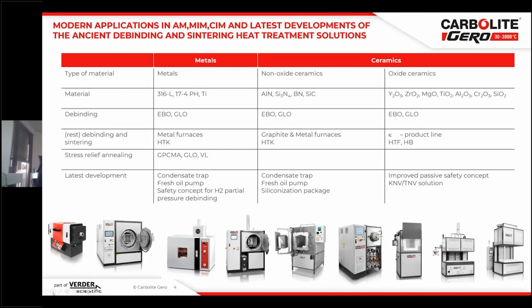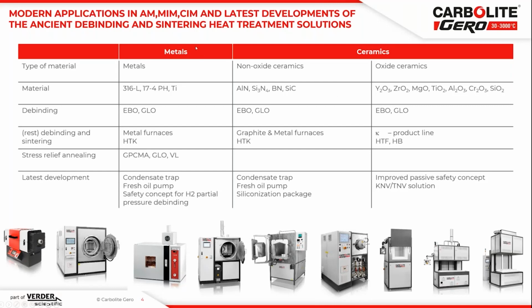Having a look at the materials, I mentioned it already. It can be metals, heat treatment for metals after additive manufacturing, but it can also be heat treatment of ceramics. And in ceramics, we distinguish non-oxide ceramics and oxide ceramics. Of course, the oxide ceramics, for instance, something like aluminium oxide or yttrium oxide. And on the non-oxide ceramic side, we talk about high-performance ceramics such as aluminium nitride or boron nitride, silicon carbide, and so on and so on. On the metal side, you see the typical materials, the typical feedstocks which are available, but also titanium, of course, needs a heat treatment. And for both metals and ceramics, we offer the solutions of debinding and sintering with a very broad range of furnaces.